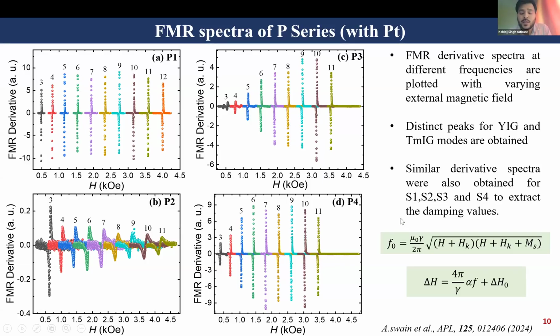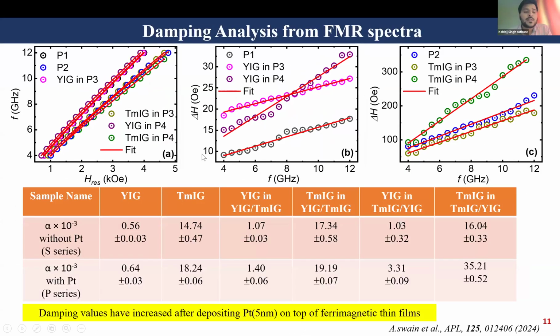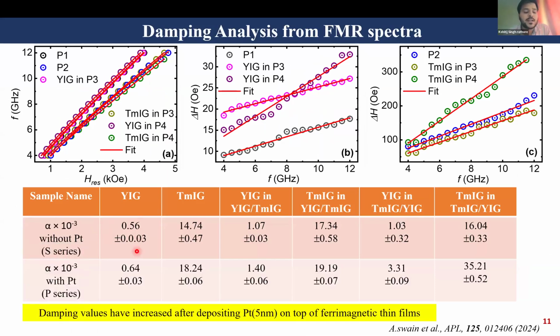These are then plotted with the corresponding frequency, which are then characterized to take out the damping parameter alpha from these samples. So from this, you can clearly see that there is a certain increase in the damping value when the platinum is deposited on the thin films of YIG, TMIG, and the YIG/TMIG bilayer. This increase in the damping value suggests the presence of some spin pumping behavior in the samples.